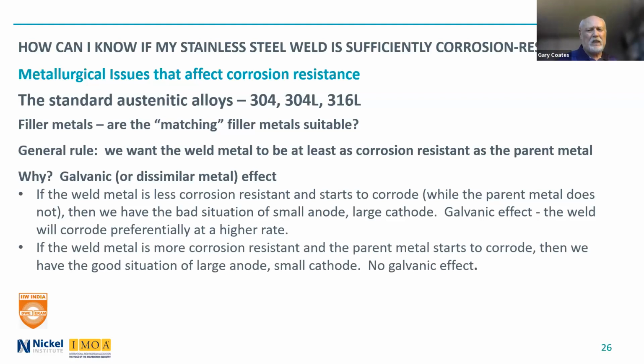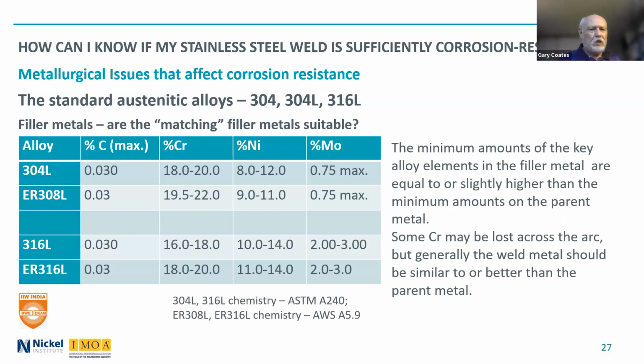So we want the weld metal to be at least as corrosion resistant as the parent material. And so I'm showing here in the table the 304L plate at the top. It has 18 to 20% chromium. The filler metal, and I took the example of the wire here, has a higher chromium content. So even if you lose some chromium across the arc, it oxidizes perhaps a bit, you will have a weld metal that is slightly higher in chromium content than the base metal.